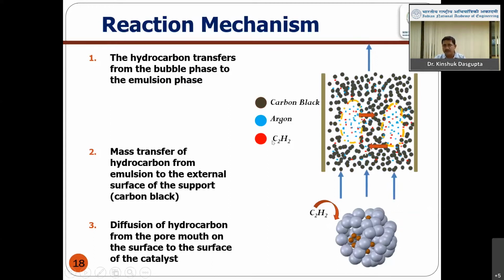In the first step, the acetylene, which is my source of carbon, is transferred by mass transfer from the bubble phase to the emulsion phase. In the next stage, from the emulsion phase there is mass transfer to the external surface of the support, that is carbon black. Then in the third step, from the external surface, the acetylene has to diffuse and reach the catalyst particles which are sitting inside the pores.